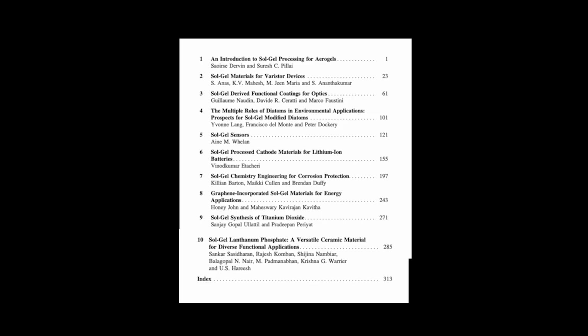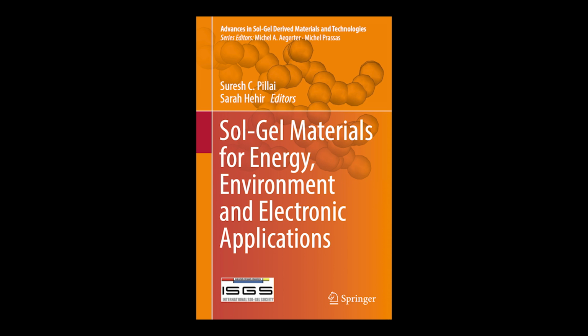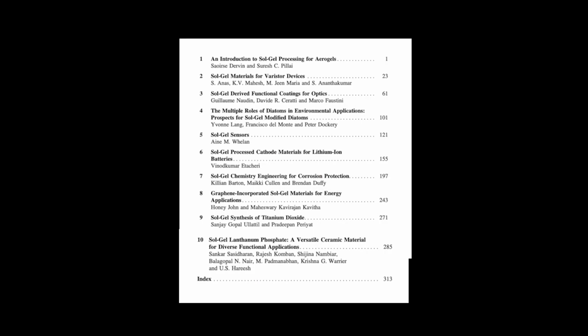And here's that surprising detail the sources highlight. The time needed for optimal aging varies wildly. Silica alkoxide gels like those from TEOS need a massive 48 hours for proper reinforcement. Yet some sodium silicate aerogels only need 3 hours. Why such a dramatic difference? That difference speaks directly to the kinetics, the speed of the precursor chemistry. Silicon alkoxides, being these larger organic molecules, well, they require a much longer time for those secondary dissolution and reprecipitation reactions to really effectively reinforce the neck regions and build a stable, interconnected network.